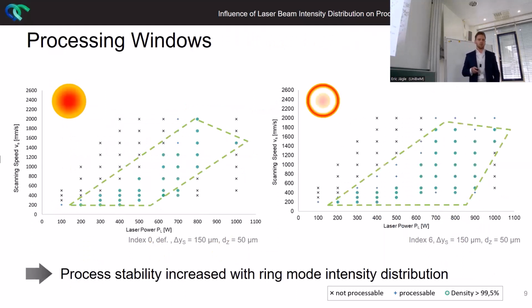As a first result, we could derive some processing windows, classified by processability and densities over 99.5%. Please note that this is just an extract and not an absolute statement of the processability of nickel-based superalloy 718. However, what we can see in the first result is that the process stability increased with the ring mode intensity distribution, probably due to fewer intensity peaks and less overheating. They were the starting point for further selection of suitable parameters to be analyzed afterwards in more detail.